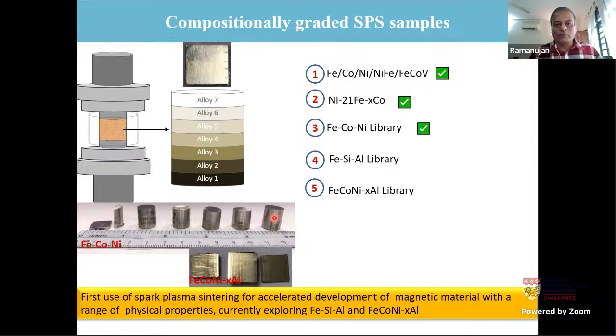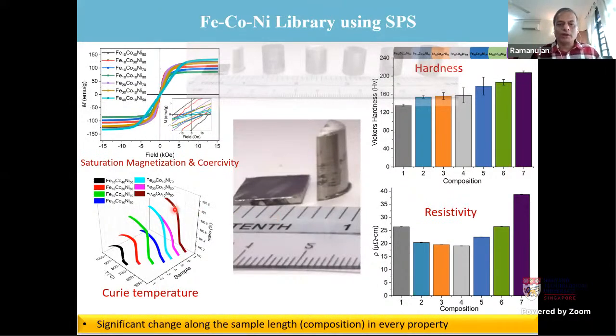So we have done this again for the case of iron, cobalt, nickel, and we could identify magnetic properties. We could identify the Curie temperature. For the Curie temperature, we've developed a home-built setup in which we use a thermogravimetric analysis system as a way of determining Curie temperature. We've published that result as well. So we can rapidly evaluate Curie temperature as well. We don't have to go through the usual PPMS route.